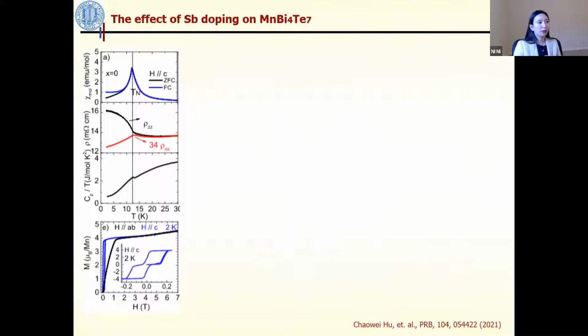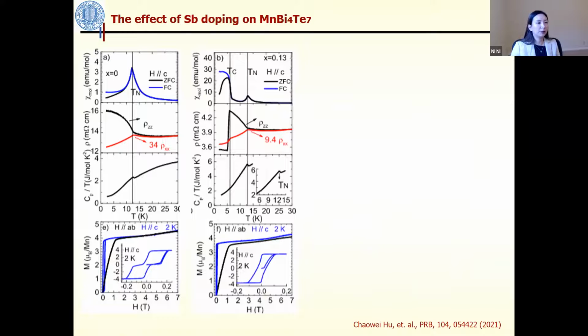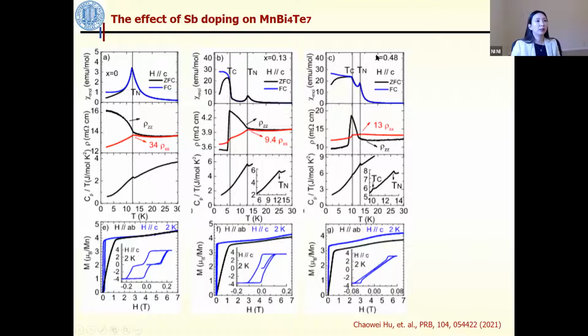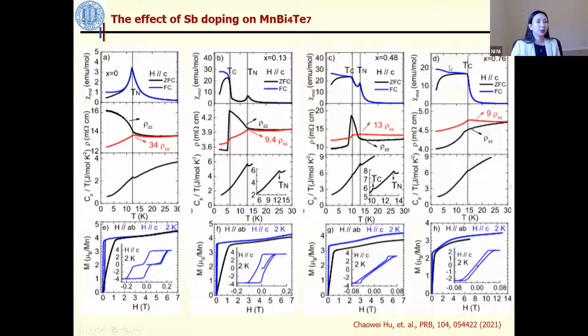Okay, so now when we dope antimony into the system, we found a pretty rich and complex evolution of magnetism. When it was 13%, you can see we started to see an extra magnetic phase transition here. And when we increased the doping level, this extra magnetic phase transition looked like a ferromagnetic type, and it was moving to higher temperature. And finally, these two ordering temperatures merge together.